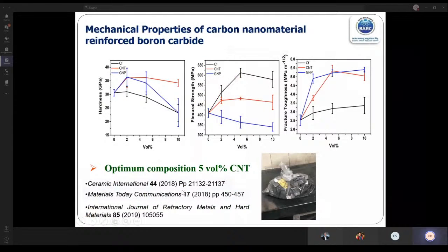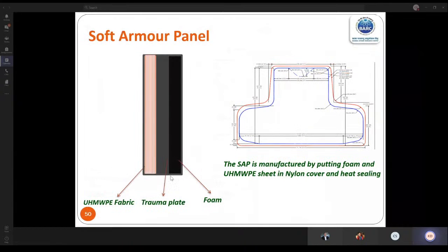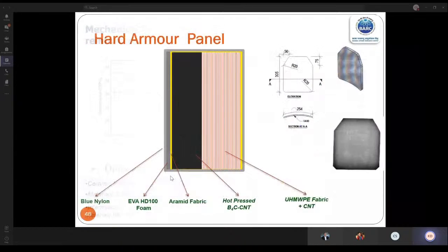And why carbon nanotube and boron carbide composite? We have done several studies and seen that three properties are important. One is hardness. The ceramic part should be harder than the bullet, and it should fragment the bullet. It should have good flexural strength and good fracture toughness. What is fracture toughness? It means it should be able to absorb the energy. So we have developed a material with carbon nanotube and boron carbide composite, which is hard enough to deform the bullet, and has good fracture toughness so that it can absorb the energy. It gets fractured itself, but it deforms the bullet. And all these fractured parts get absorbed in the backing material. I'll show you, this is the backing material, where the fragmented part will be captured.